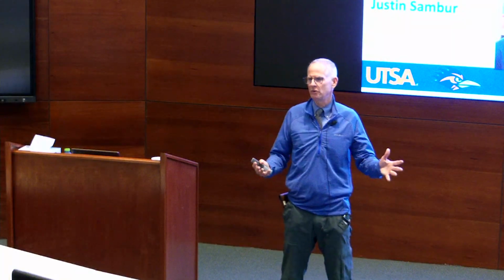Thank you very much. Yeah, so I didn't talk at all about synthesis, and I could spend half of the time talking about synthesis, obviously. The way that we most commonly make these polymers, well, there are 2 approaches. One is what I call the direct approach, where we take an ionic monomer, maybe a sulfonated monomer, and we polymerize it. Most often these are step growth polymerizations. We use metal catalyzed coupling chemistry like Suzuki or Sonogashira type reactions. When we do a direct polymerization, unfortunately, we don't have an easy way to get molecular weight, because polyelectrolytes don't do typical GPC analysis.